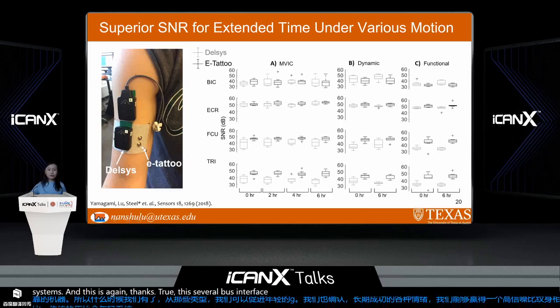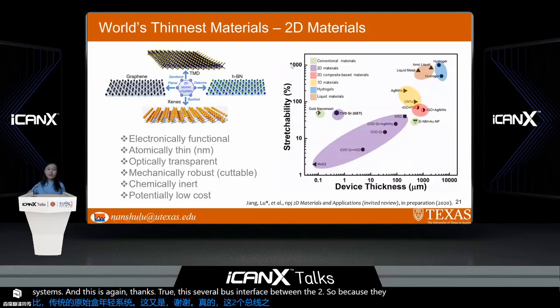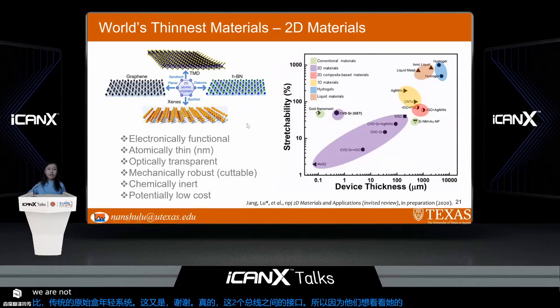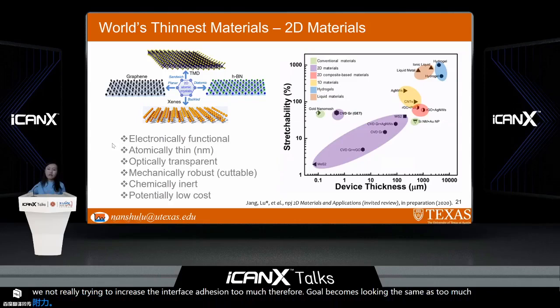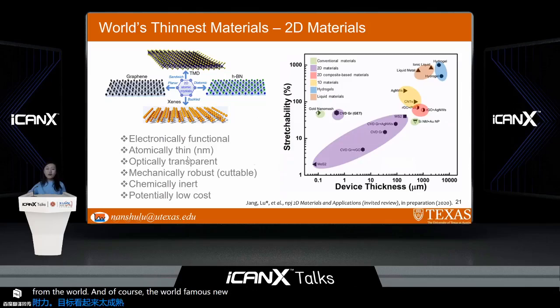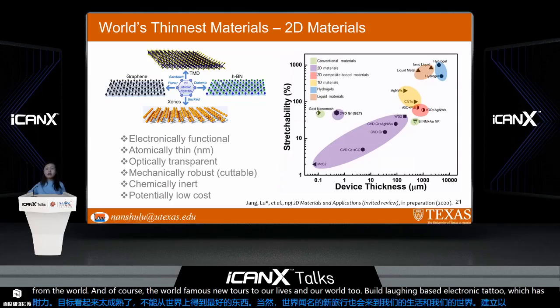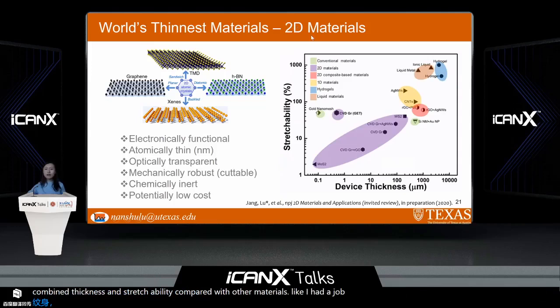Therefore, because the bioelectronics interface is so important, and we are not really trying to increase the interface adhesion too much, the goal becomes looking for the thinnest material to have the best conformability. And of course, the thinnest materials are 2D materials, and we are able to build a graphene-based electronic tattoo, which combines thinness and stretchability, compared with other materials like hydrogels and liquid metal. They are very stretchable, but usually the devices made out of them have a certain thickness.